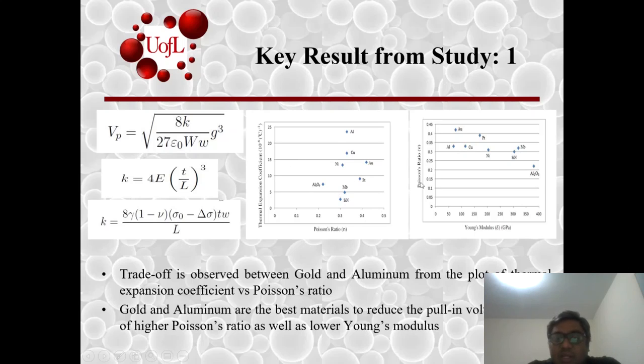And the third plot is related to the Poisson ratio versus Young's modulus. So here they're looking for that material for which the Young's modulus is very low, and they found that the gold and the aluminum have the lower Young's modulus and they have also high Poisson ratio. So they have concluded that based on this plot, the gold and the aluminum are the best material to reduce the pull-in voltage because of their high Poisson ratio as well as the lower Young's modulus.